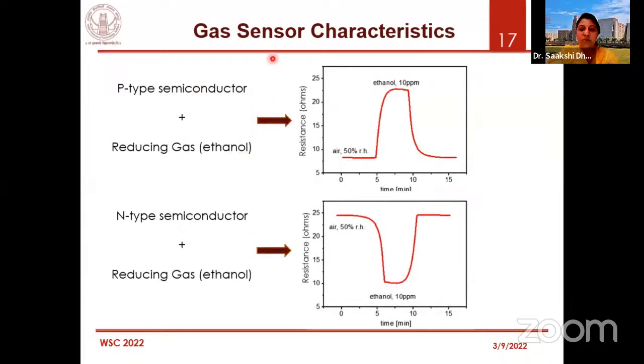So coming on to sensor characteristics, how we read them, right? What we do is we have our sensor material with electrodes, and we then expose it to a reducing gas. Now, the first impression of the sensing curve can tell us what is exactly happening in the material. So we keep this reducing gas fixed, right? And as we expose our sensor to the gas, we see, say, a change in resistance, which is an increasing resistance. At that moment, this gives an idea that the material that we have made is P-type. And if we see a decrease in resistance with the same gas being exposed, we understand that the material is N-type. So this is one short way to know whether it is a P-type or N-type material. And of course, the other way is that we do Hall effect measurements and we understand the dopant and the dopant concentration from that experiment.